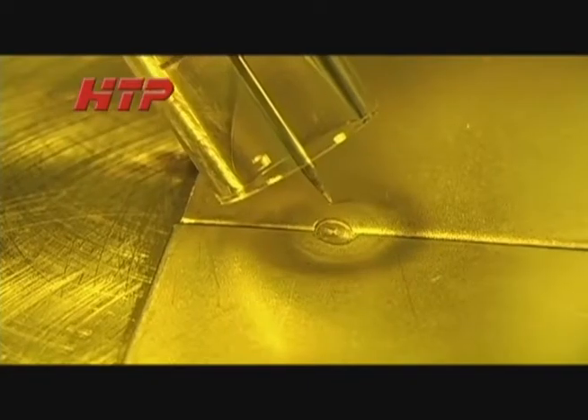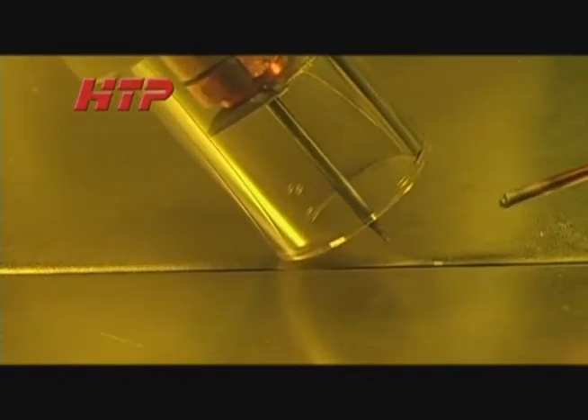Depress the pedal to start the arc. Increase the arc by pushing the pedal further until you get a molten puddle, and dab the filler to make the tack. Repeat the process every 2 inches or so.